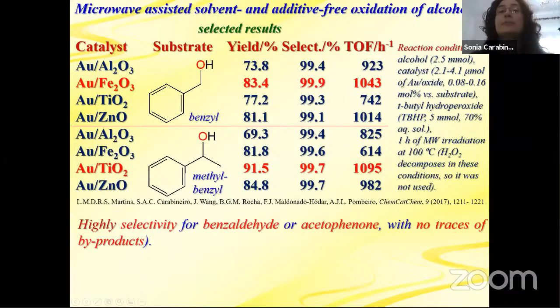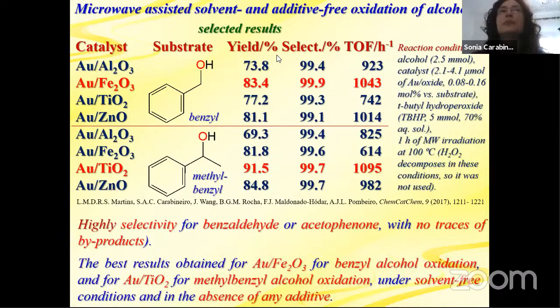So very high selectivities. And the best results, like I said, were obtained for gold on iron oxide for this benzyl alcohol oxidation, and for gold on titanium dioxide for methyl benzyl alcohol oxidation. Again, solvent-free conditions in the absence of any additive. So it was 1 hour reaction in microwave irradiation at 100 degrees, and we had to use the tert-butyl hydroperoxide because H2O2 decomposes in these conditions.